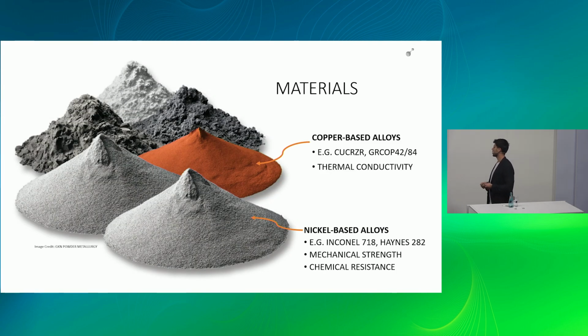When you design a rocket engine, usually you have to do a big trade-off between different materials. Classically, it's either copper-based alloys or nickel-based alloys. Copper-based alloys like copper-chrome-zirconium, or GRCop from NASA, are usually used if you have a very high requirement for thermal conductivity, which is the case for rocket engines. The nickel-based alloys are usually used when you have requirements for very high mechanical strength and chemical resistance. For rocket engines, both is the case. So usually if you develop these engines, for example, the combustion chamber, which is the heart, you have to decide between these 2. And that is actually a big trade-off in a thermomechanical way. You do very big thermomechanical analysis between the materials, and then in the end you find out which one is the best for your engine.